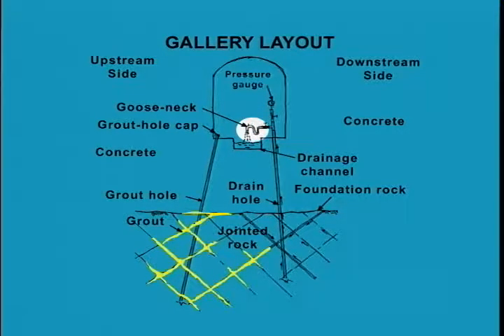Holes should be provided with a rigid plastic pipe outlet with fittings to allow a valve to be closed and water pressure measured when desired. Drains should also have reverse goosenecks so that air cannot enter the drain hole and promote precipitation of minerals — primarily iron but also other oxides. Drains may also be provided with a double perforated casing and the inner pipe wrapped in filter fabric, in zones of possible erosion and piping of fines such as in weathered rock or fault zones. To prevent seepage from exiting the abutment area just downstream, special methods may be taken: covering the area with an inverted filter drain, or drilling drain holes into the abutment.